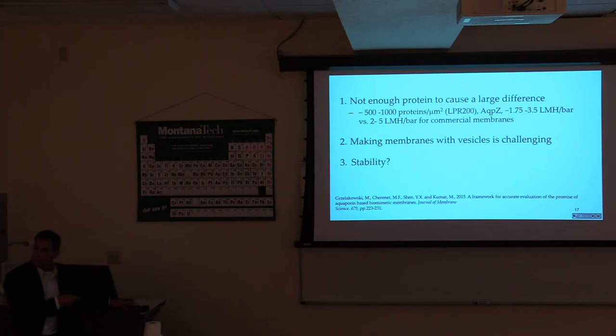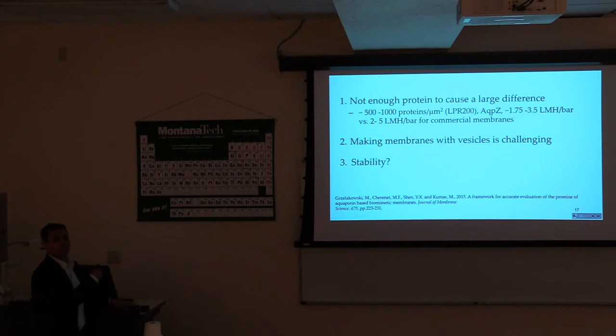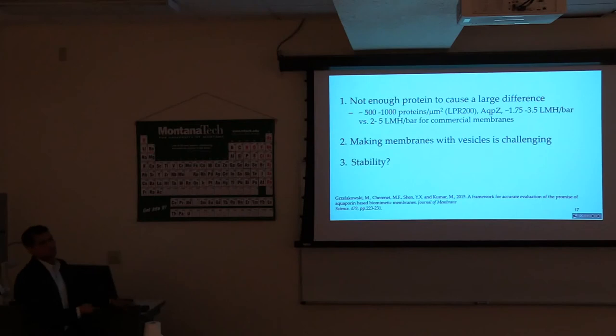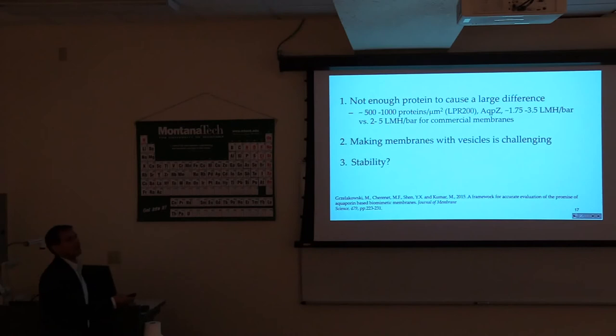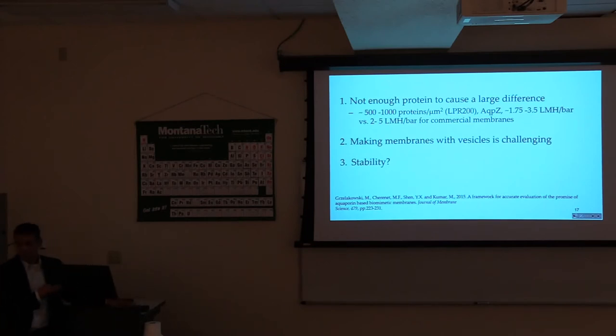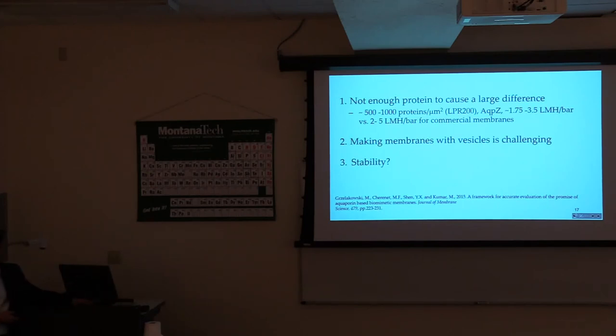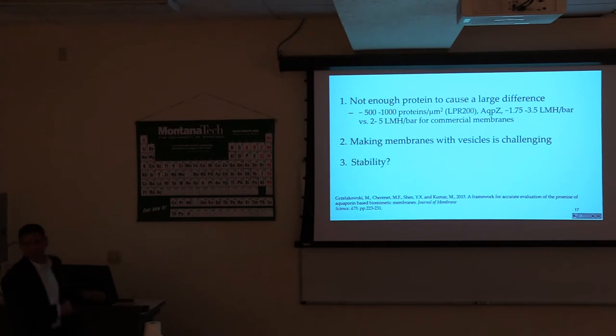So we should not see any improvement if you use those vesicles to make those membranes — the fundamental calculation is just wrong. And making membranes with vesicles is hard. A recent study showed that only four percent of the vesicles you add actually make it into the membrane. So this procedure has issues in addition to the big question: how long do these proteins really last in a commercial system?